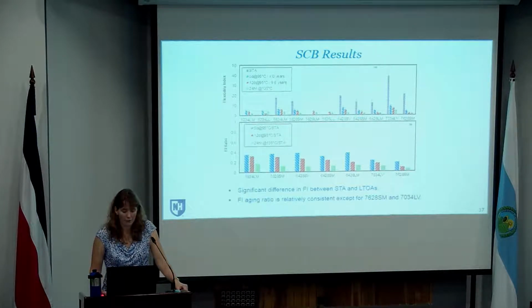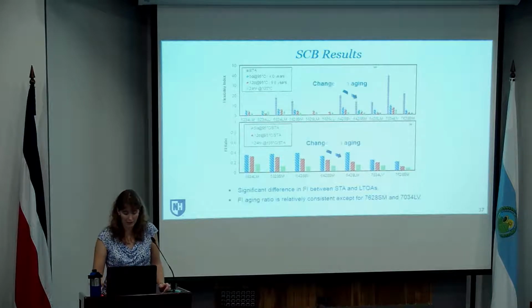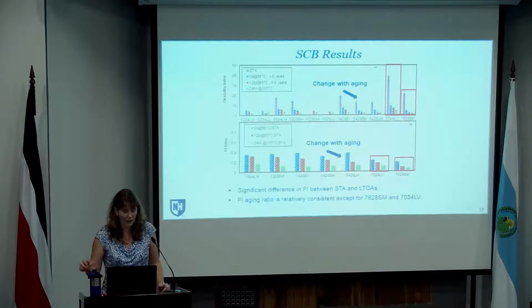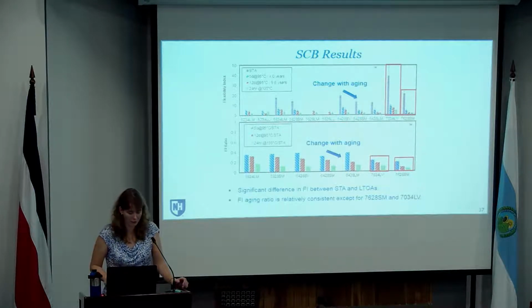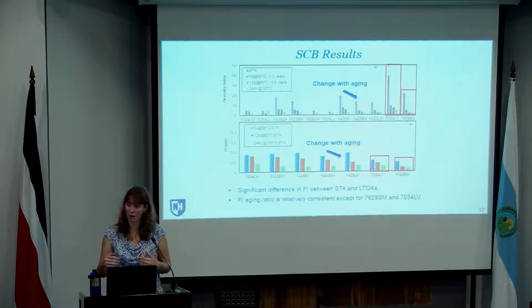And then you look at the bottom figure, and again, we're looking at the ratio. So you can see with the SCB, with the aging, we're getting a pretty big drop in the SCB results in terms of the flexibility index. And again, with these, you're seeing the change in the aging, and you're seeing different type of behavior with those polymer modified materials than you are with the others. But still, if you look at the actual flexibility index values after aging, they're still higher than a lot of the traditional mixtures. So even though you're seeing a higher drop, still in the end they're better.